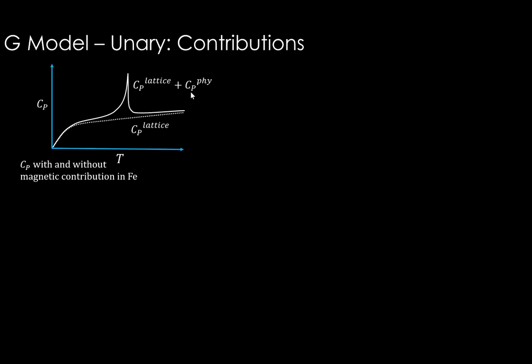And if we have the Cp, there is a way to reach Gibbs energy from Cp, right? If you integrate Cp dT up to a particular temperature of our interest from a different temperature, we get the H value at that temperature, and entropy is the integral of Cp by T dT. Once you have the enthalpy and entropy, you can put them into this kind of equation, G equals H minus TS, at the temperature of interest, and you can get the Gibbs energy.